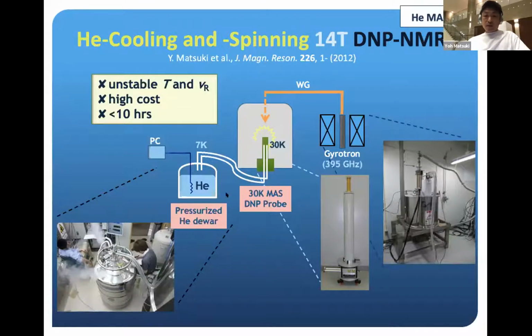So first, we started out building this liquid helium boiling off spinning system for ultra low temperature DNP. It took some time, but we suffered with this system from unstable temperature and spinning, and relatively high cost for doing measurements because we were boiling off a lot of liquid helium. And also it lasted only less than 10 hours or so each time because we couldn't refill this pressurized helium dewar while doing the measurement. So it was a lot of fun, but it was too experimental a system. It's not for routine DNP measurement for biological things, which needs long and stable measurement time.